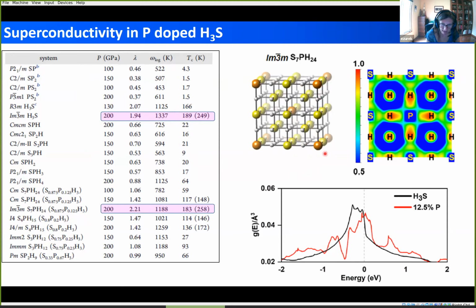Here I show the candidate with the highest TC, which in our calculations was found to have a very similar TC to that of H3S. I show two numbers here: the ones in parentheses are solutions to the Eliashberg equations, and the ones without parentheses are just the Allen-Dynes type equation.